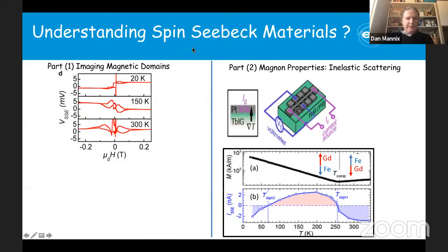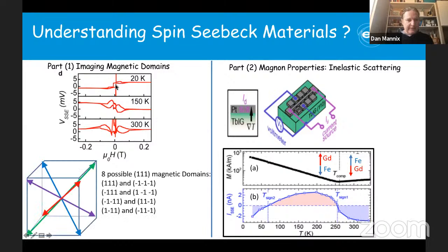So if we look inside these materials when we measure the spin-Seebeck effect, there are two sort of strange effects that really come on. And this is the first part that I want to address. If you apply the magnetic field, and this is the spin-Seebeck voltage that you measure as a function of applied magnetic field, you can see that it's actually very noisy at zero field. It's got this kind of hysteresis effect, and it seems that there's some kind of quenching of the spin-Seebeck voltage as you go to zero field, and that kind of suggests that there are maybe some domains inside the structure. It looks very much like a hysteresis. It's suggesting that there are some kind of domains acting in a way that makes the efficiency not very strong inside these materials.